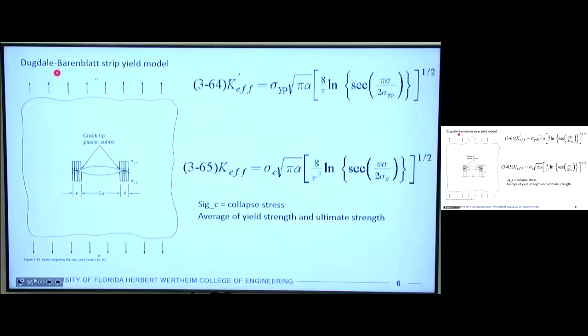And so I'm going to talk about this short model here, which is more of a conceptual model, but it allows for some quantitative approximations, which is helpful. So this model is called the Dugdale-Barenblatt strip yield model, and you can see it represented here on this 2D plate. So before we had a crack tip, right? So this is a center crack through the thickness of a plate.